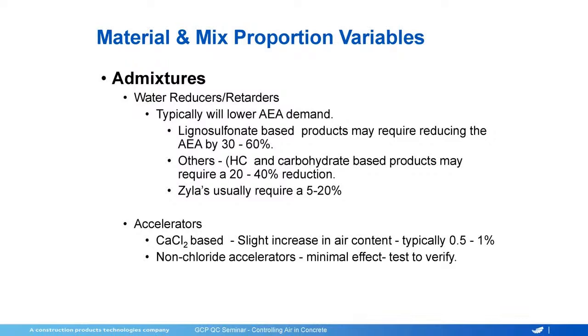Calcium chloride can cause you to increase slightly. I don't know that you guys would use a lot of calcium chloride, but they typically don't have a big impact. Now, non-chloride accelerators, yes, typically it's a minimal impact, but if you're using hot water, non-chloride accelerators, and you're trying to get air entrainment, you can struggle. And a lot of that's going to come down to dosing sequence. And dosing sequence makes a difference in general, but when you're doing hot water and non-chloride accelerators, you really can have a huge impact on the air.